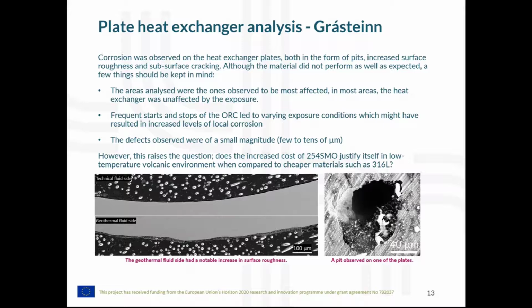But as you can see, on the pictures there on the bottom left, you can see quite well the notable increase in surface roughness of the geothermal fluid side in comparison to the technical fluid side. And then on the bottom right, you can see one of the largest pits that we observed on the plates. But the results here, although that 254 SMO material behaves not badly and can be used for a number of years there at Grásteinn, it does raise the question if the increased cost of more highly alloyed material such as 254 SMO does justify itself in low temperature volcanic environment when we compare it to cheaper austenitic steels such as 316L. But that's a question to look into.